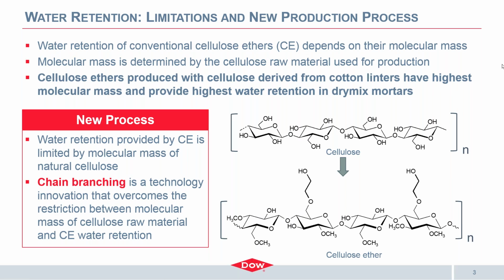Water retention of conventional cellulose ethers depends on the molecular mass of that product, and that again depends on the molecular mass of the cellulose that's used in the production process. And the molecular mass of cellulose is defined by nature. So cellulose obtained from cotton linters, that's one source, others certainly wood, has the highest molecular mass. Consequently, cellulose ethers produced with this material provide the highest level of water retention. And these cellulose ethers also have the highest aqueous viscosity, which our industry uses as a measure for molecular mass and consequently also for water retention efficiency.